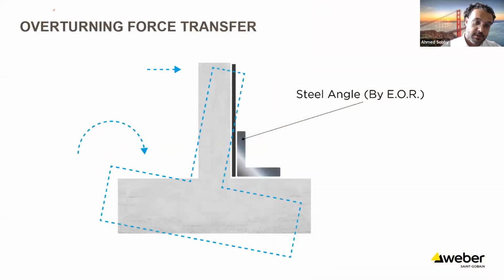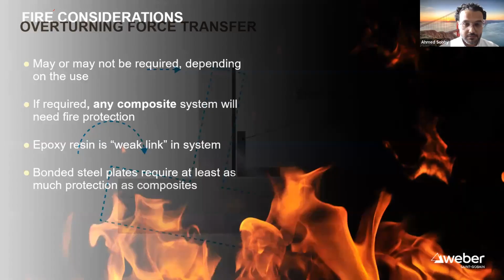One of the most interesting applications that we come across is the overturning force. For instance, imagine that this is a diaphragm wall, and for some reason we want to increase the structural capacity of this wall. This is one of the instances where we need to be very careful of placing steel in close proximity to carbon fibers. In this instance, the designer opted for using carbon fiber and a steel angle at the bottom of the wall to increase its capacity. Putting carbon in close proximity to steel will actually encourage the steel to create a corrosion cell, and this is why we always recommend using a separation layer, either of structural adhesive or an epoxy layer, or glass fiber reinforced polymer, to come in between.